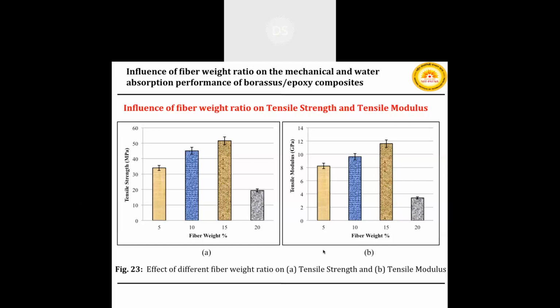The Borassus fruit fiber composites of 15% fiber weight ratio obtained 51% and 165% higher tensile strength than 5% and 20% weight ratio of Borassus fruit fiber respectively. Similarly, 51% and 240% higher tensile modulus were obtained for the 15% weight ratio composite as compared to 5% and 20% weight ratio of Borassus fruit fiber composite respectively.